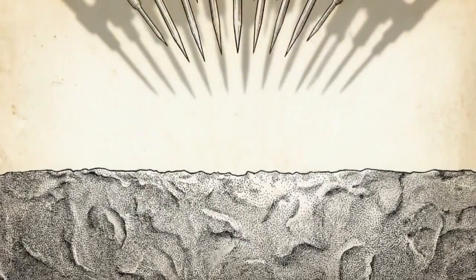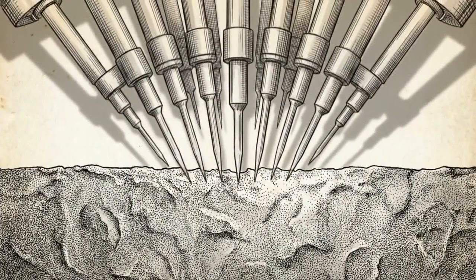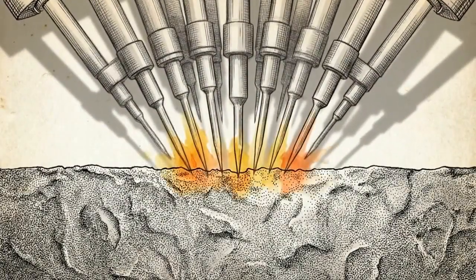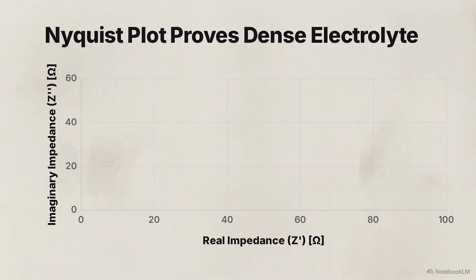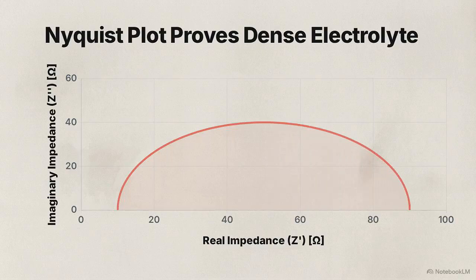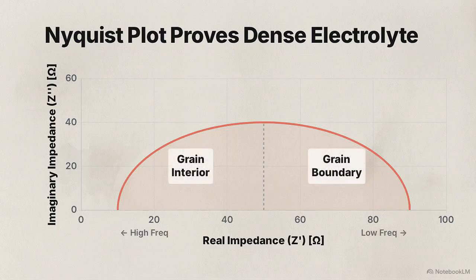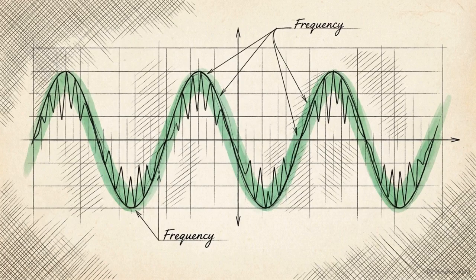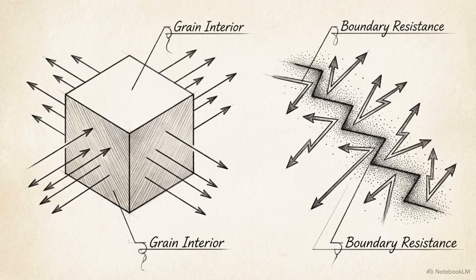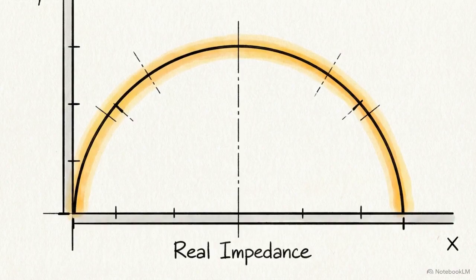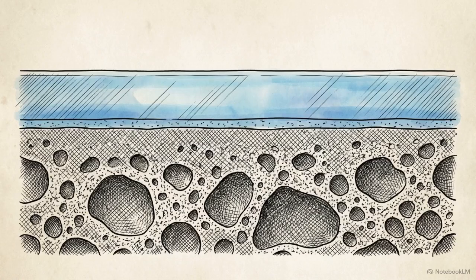A visual inspection under a microscope is insufficient to verify the seal. The success of the densification must be proven electrically. This chart displays the results of impedance spectroscopy. This technique sends alternating currents through the material to measure its electrical resistance at different frequencies, plotting the data as a Nyquist semicircle. Because different structural elements react to specific frequencies, the measurements isolate the exact resistance of the solid grain interiors from the resistance of the boundaries where the grains connect. The impedance data confirmed high ionic conductivity with minimal boundary resistance. The loose grains had successfully fused into an unbroken solid electrolyte.